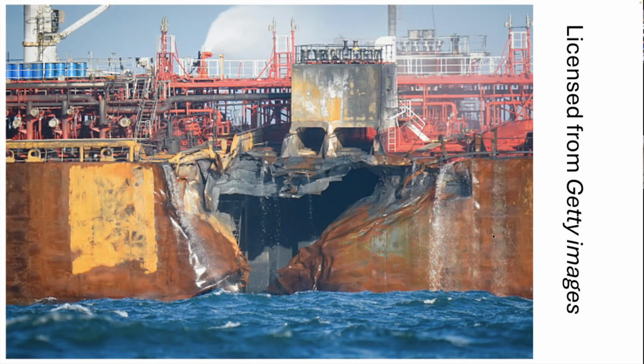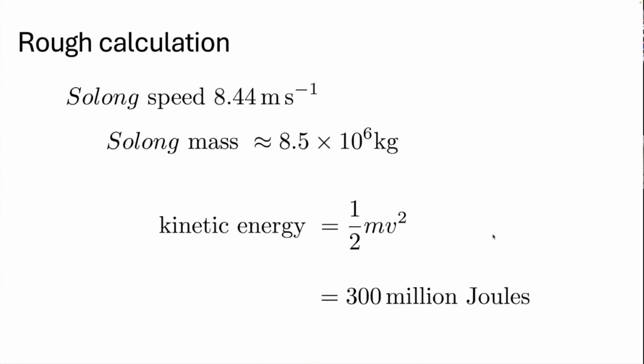So I'm going to demonstrate this with a short calculation. So this is undergraduate stuff where we know the speed at which the Solong was proceeding. It was 16.6 knots according to the interim report of the National Maritime Agency, and I've converted that into meters per second. And it weighed approximately 8.5 million kilograms. So you can work out the kinetic energy of the Solong, which comes to about 300 million joules. And that kinetic energy must be absorbed by the Stena Immaculate tanker.